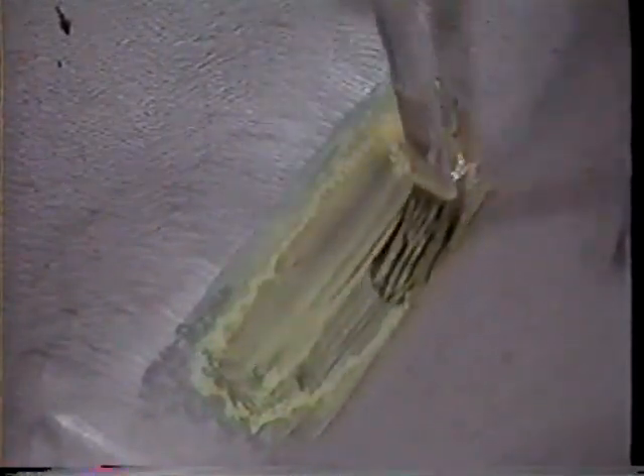Apply 2 coats of the epoxy primer called out in the TM. Also, be sure to follow all the safety and repair procedures called out in the TM. Note that when the primer is applied in high humidity, the primer may not adhere well to the surface. This might cause eventual debonding. When the primer dries, apply 2 coats of top coat. Again, follow the procedures called out in the TM.